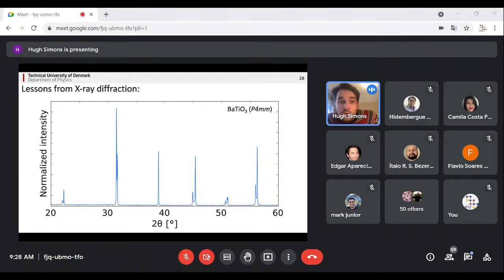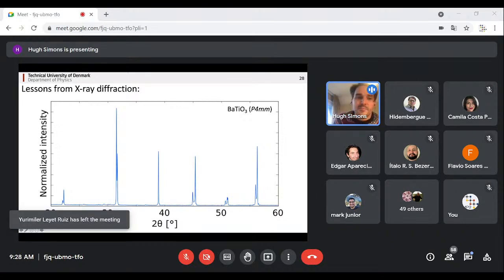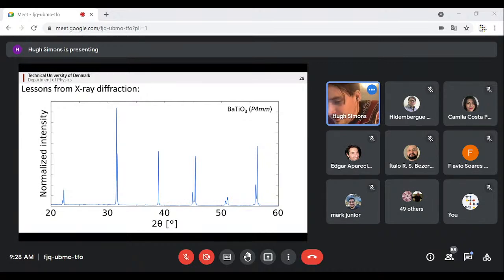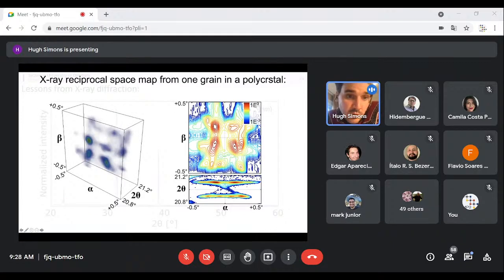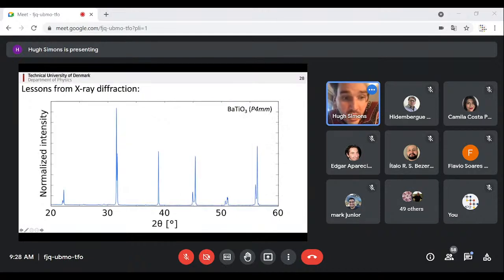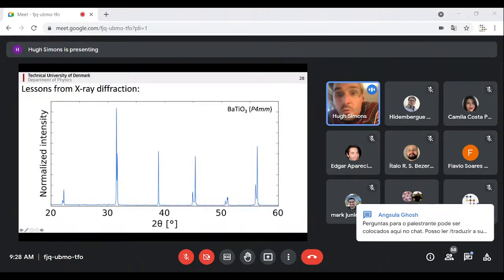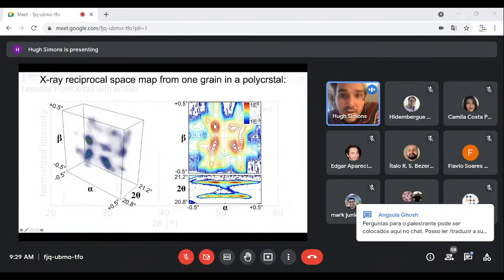That's all well and good. And I spent my whole PhD basically doing X-ray diffraction studies on barium titanate. So I've completely trusted this. But then one day we were doing some studies of this barium titanate, and we made the mistake, or perhaps the stunning realization of looking, in fact, at the individual diffraction spot created by not just a powder diffraction scan, which is a sum of all the different grains in the sample, but of just one individual grain.